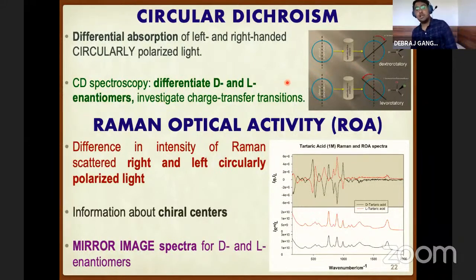And this was further developed into vibrational optical activity, or VOA, which has two parts. One is vibrational circular dichroism, where there's a difference in intensity of right-handed and left-handed circularly polarized light when they are absorbed in IR spectroscopy, and we get a difference in spectrum. And the other one is Raman optical activity. In Raman optical activity, the Raman scattered light by left and right circularly polarized light has different intensity. And this difference in intensity, or IR minus IL, when it's plotted, shows us some positive and some negative peaks.